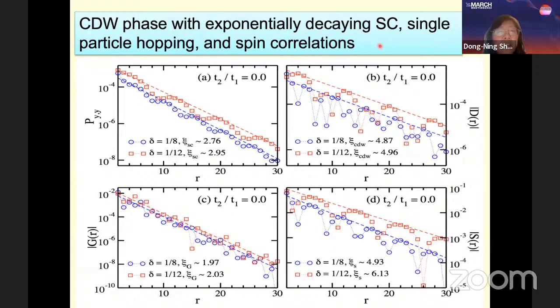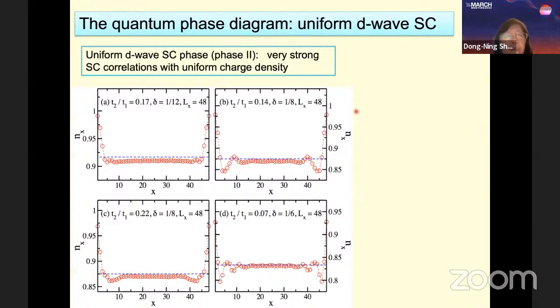If we look at the single particle and spin correlations, they both decay exponentially, even when we scale those results to infinite bond dimension. So those characterize the insulating CDW phase.